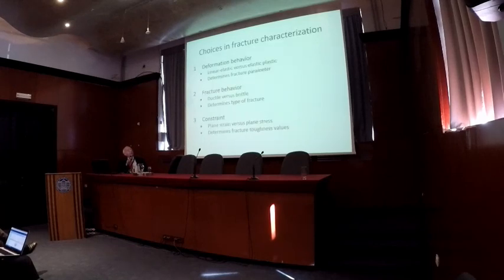So here are some of the things that you can do in fracture characterization. And this is kind of my own way of laying things out. Can talk about deformation behavior. So essentially you have linear elastic deformation, that is limited plasticity, and then you can use the K. Or you have too much plasticity, then you need J or the CTOD. And that's the deformation behavior. The fracture behavior you worry about is whether the fracture is ductile or brittle. If it's brittle, you get a well-defined fracture point, but if it's ductile, you have to do the R curve analysis with perhaps getting a single point there.